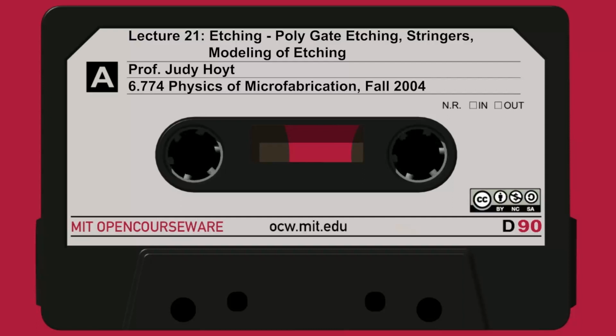These oxides won't etch if the etchant is highly selective to oxide. So if you're using a single etch gas that is very selective to oxide, which is what you might want to do for the poly, that same etch gas might not do very well on the tungsten silicide. And what happens when you use an etching gas that is very selective to oxide and you don't do a breakthrough? If you have any native oxide on top of that structure and you don't break through it, you'll end up with something called RIE grass.